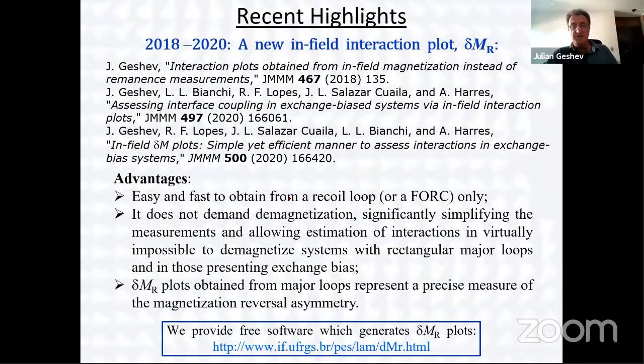Insights, maybe a new method of estimation of interactions we developed a couple of years ago. It's a delta MR, which is based on recoil curves instead of remanence curves. It's rather fast, much faster than the remanence curves. It does not demand demagnetization, so you can apply it on systems that are virtually impossible to demagnetize, like systems with rectangular curves. Also, you can use it as a measure for the reversal asymmetry.